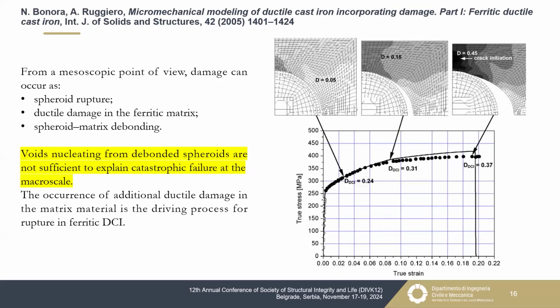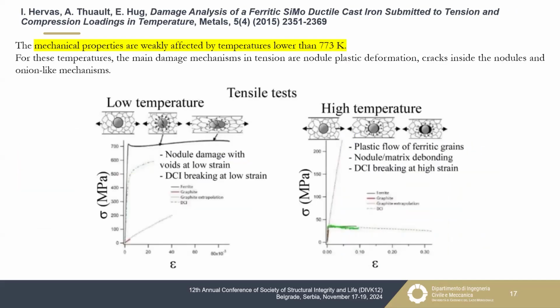From the point of view of the simulation, other authors, also from Cassino, found that the damaging mechanism inside the ductile cast iron should be modelled using a different sequence. I mean, a spheroid rupture followed by ductile damage in the ferritic matrix and by the spheroid matrix debonding. Also in this case, the numerical results were not so bad. So it is rare that, using different analyses of the damaging mechanism, the numerical approach was always able to simulate the process.